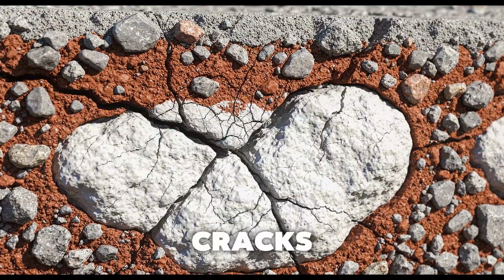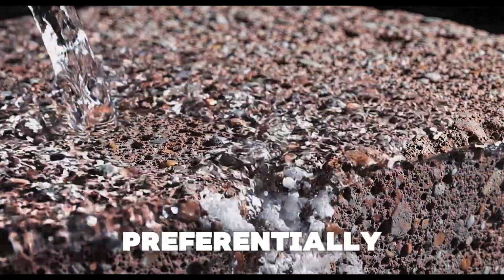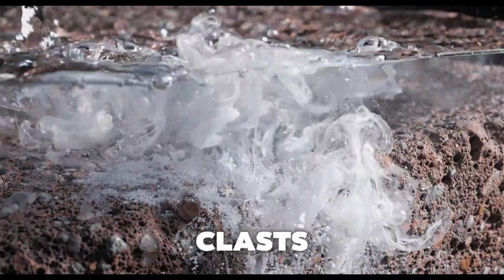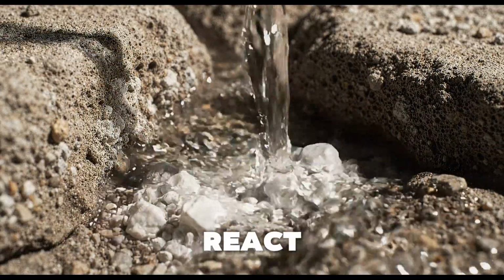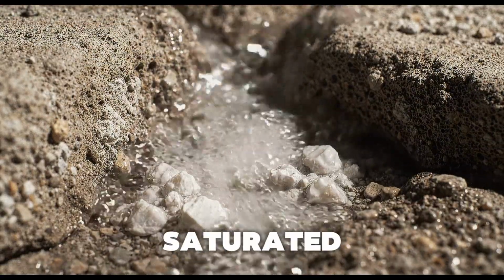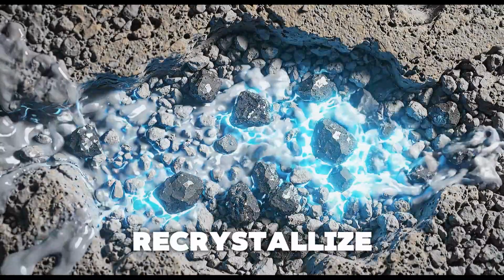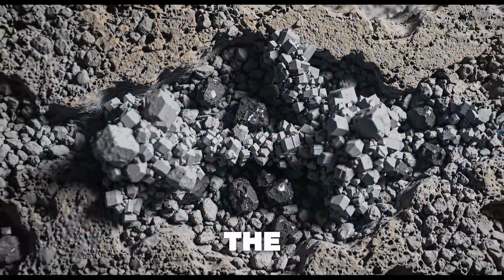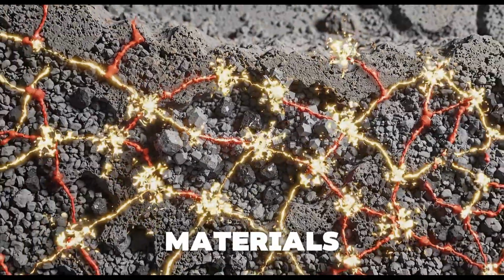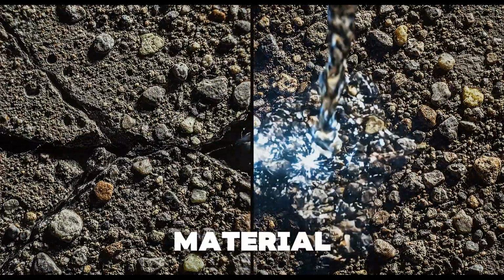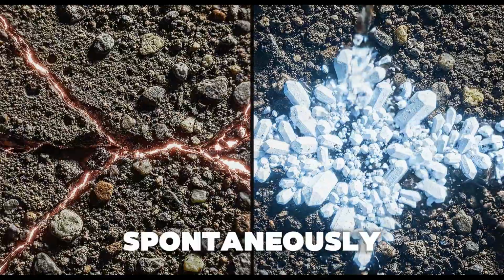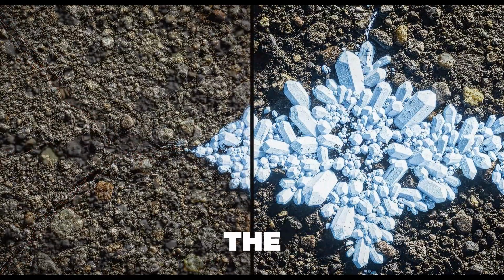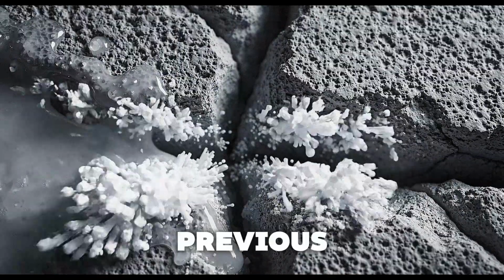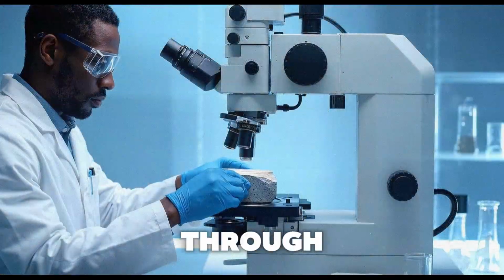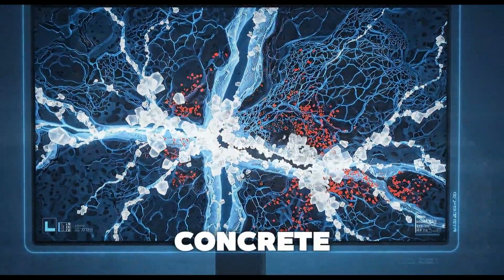As soon as tiny cracks start to form within the concrete, they can preferentially travel through the high surface area limeclasts. This material can then react with water, creating a calcium-saturated solution, which can recrystallize as calcium carbonate and quickly fill the crack, or react with pozzolanic materials to further strengthen the composite material. These reactions take place spontaneously, and therefore automatically heal the cracks before they spread. Previous support for this hypothesis was found through the examination of other Roman concrete samples that exhibited calcite-filled cracks.